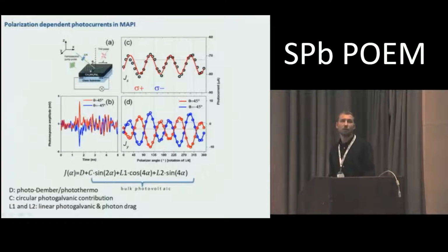And again, we use this material to generate photocurrents using the methods which I told you before. It's a very similar setup to the one we used to study other materials. And again, we can obtain photocurrents which demonstrate clear dependence on both linear polarization, especially seen in the transversal geometry of the experiment, and helicity dependence.